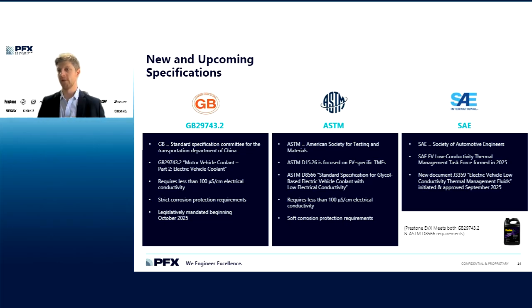So GB 29743.2. And again, this is the standard specification committee out of China, who represents the transportation department. This specification in particular calls out 100 microsiemens as the maximum electrical conductivity for the fluid. So you'll remember from about 2 slides ago, we saw that a conventional or a traditional internal combustion engine has an electrical conductivity between 2,500 and 5,000 microsiemens per centimeter. So we're looking at orders of magnitude decrease in electrical conductivity.